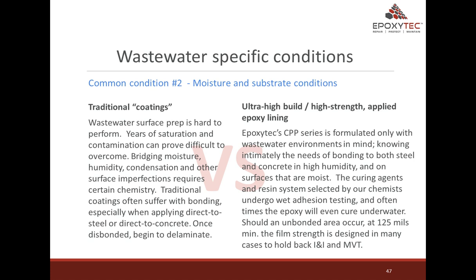Common condition number 2, moisture and substrate conditions. Traditional coatings. Wastewater surface prep is hard to perform. Years of saturation and contamination can prove difficult to overcome. Bridging moisture, humidity, condensation, and other surface imperfection requires certain chemistry. Traditional coatings often suffer with bonding, especially when applying direct to steel or direct to concrete. Once disbonded, they begin to delaminate.